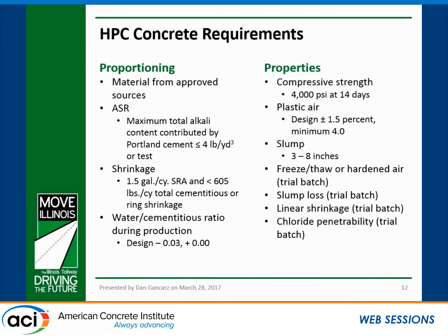So some of the properties we evaluate for our HPC mixes, we're looking for 4,000 psi at 14 days. Plastic air, we allow a minimum of 4.0, and then the producer sets their design, and they're kept to a 1.5 tolerance. Slump is similar. The allowable range is 3 to 8, but they're held to a 1.5 inch tolerance during construction.